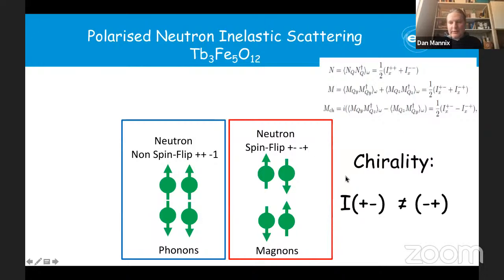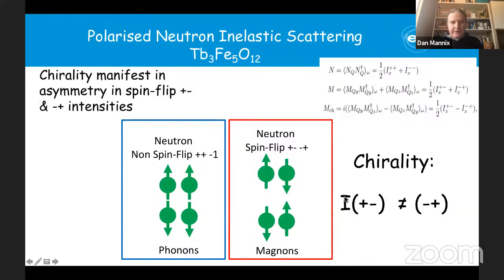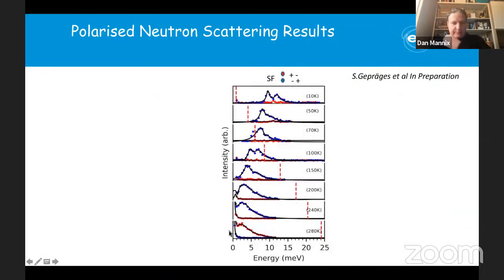And where you can get chirality information in neutron scattering is a difference. If you have an asymmetry in the intensities of up and down, that will tell you about chirality. And that's really where we come into this, looking at these materials with inelastic neutron scattering. What you see here are the magnon modes, which are measured as a function of temperature. First of all, there's a gap that opens up and it goes above the thermal energy, which is shown by the vertical line here. And you can see that there's a chirality. It's very clear because one channel is finite, the other channel is essentially zero. So that's telling you that these modes are essentially 100% chiral, very strongly chiral. And at the compensation temperature, they switch over. The red becomes blue as you go through that compensation temperature.